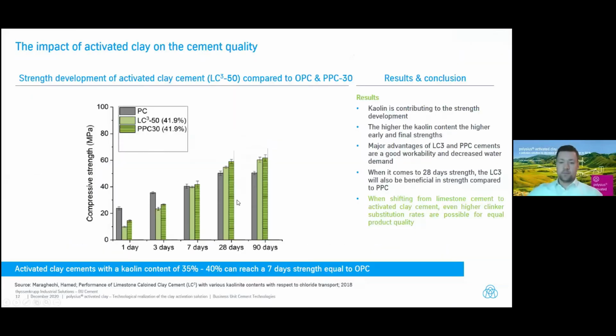So what we see is that the strength of this activated clay cement is typically, especially when talking about the early strength development, lower compared to OPC. But it's in the same range compared to limestone cement. So especially after 7 days, you see that the strength of these cements is equal to OPC, but with a clinker of only 50% in this case. So it's a quite low clinker content, but a very good strength. And even after 28 or 90 days, the strength will exceed the OPC. So these are very good results.